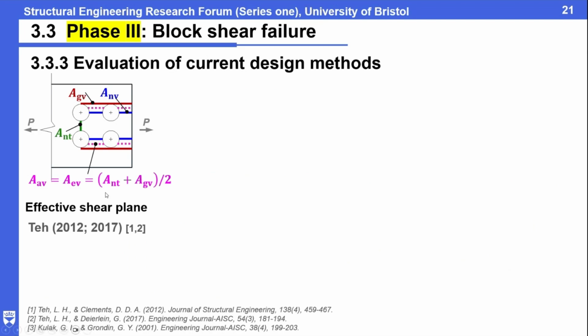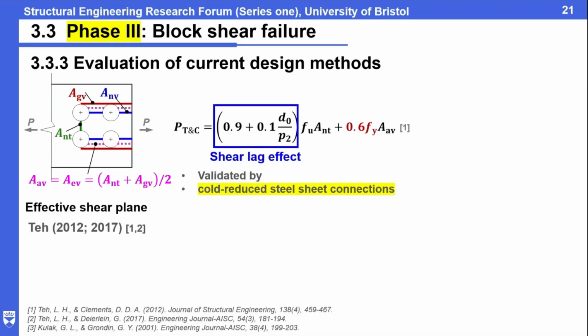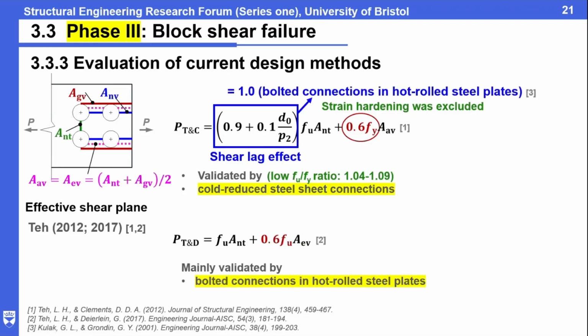We do it like this. First is based on the proposed equation from other researchers. So Teh from Australia, they proposed an equation for the cold reduced steel sheet connection. They mentioned that actually just using the shear plane like the average of the net and gross, and then for the shear strength, just use 0.6 Fy. They just exclude the strain hardening. This is for the cold reduced steel. And they actually propose another. For the hot rolled steel, they think, okay, the strain hardening is actually fully developed, and then we can consider just using 0.6 Fu.